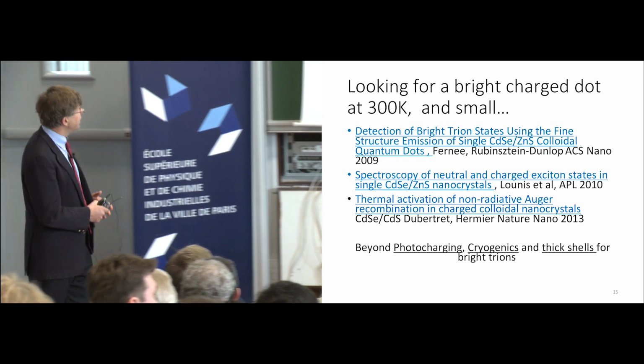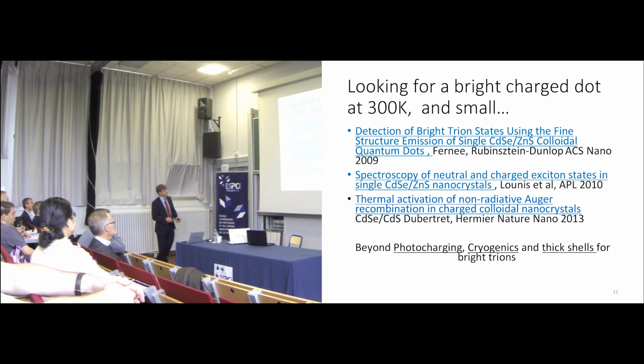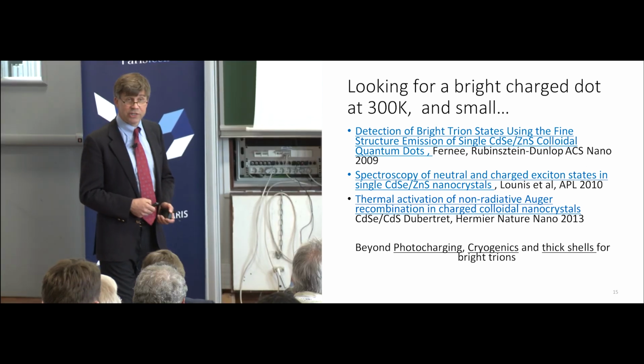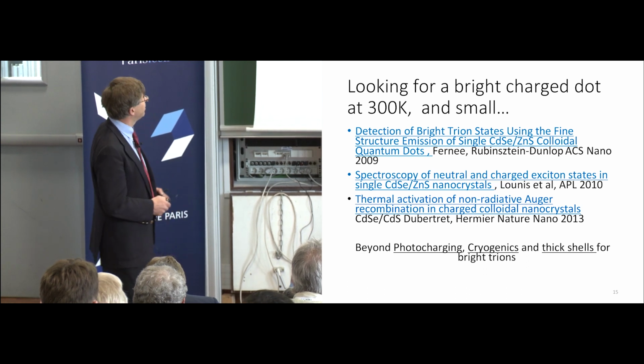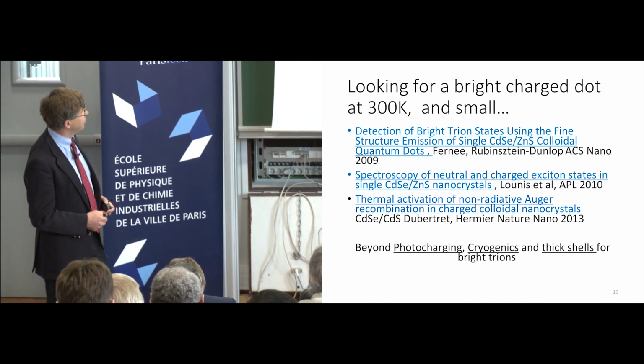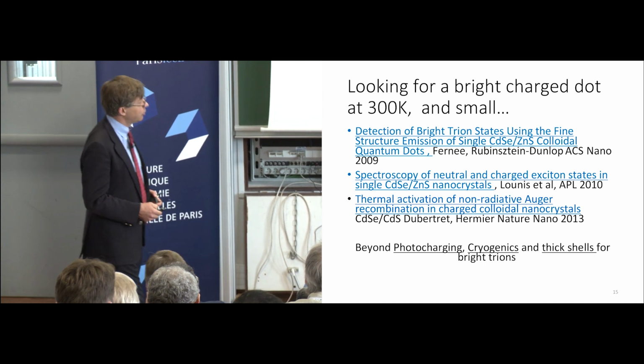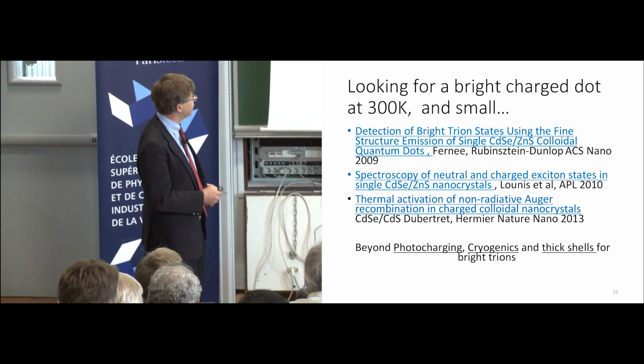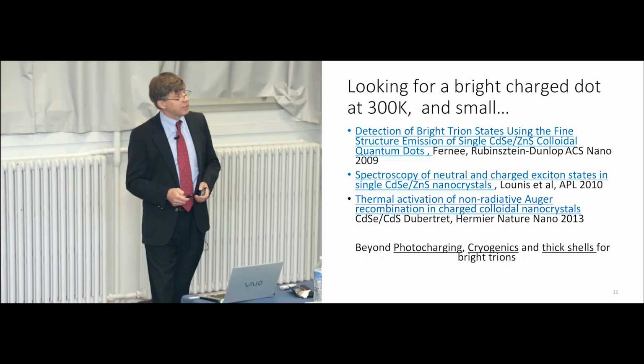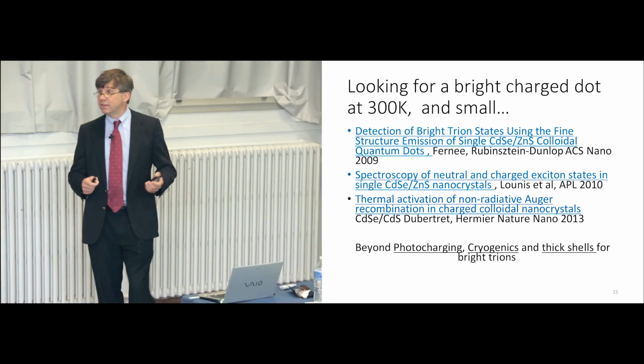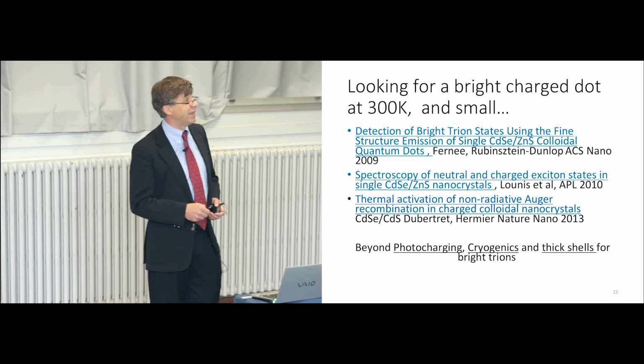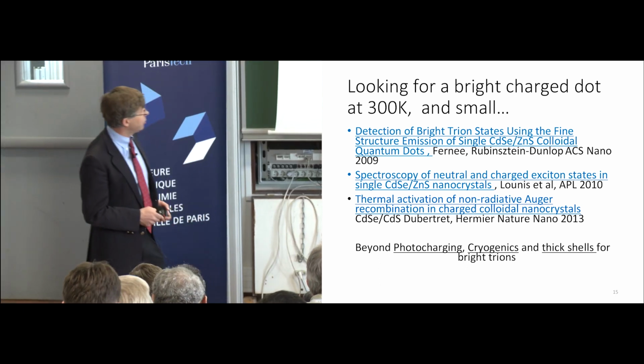And we were not the only ones. There was some work in the literature that started to show that negative trions were also bright. There was this work by the people down under in Australia. They found that they could look at a single dot at cryogenic temperature and see lines that were associated with charged dots. And there was the work by Lounis, which also showed charged dots. And of course, there was the work by Benoît Dubertret and Hermier, where they saw this amazing thing that a charged dot could have 100% quantum yield. All of those were low temperature.